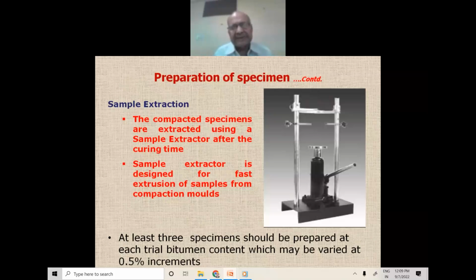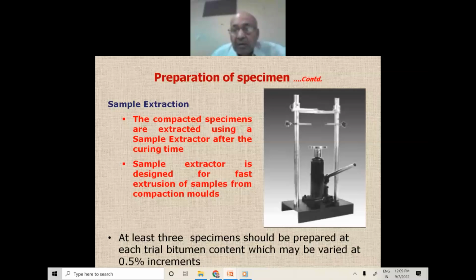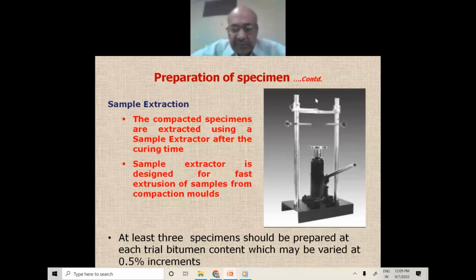The dry mix of the aggregate and the filler is heated to a temperature of 150 to 160 degrees centigrade. The compacted mold assembly and hammer are cleaned and kept preheated to a temperature of 100 to 140 degrees centigrade. The bitumen is heated to a temperature of 150 to 165. Samples are prepared, 3 each at each bitumen content with the first trial percentage of the plastic waste and the bitumen. The mixing temperature of the VG30 is about 165 degrees centigrade.